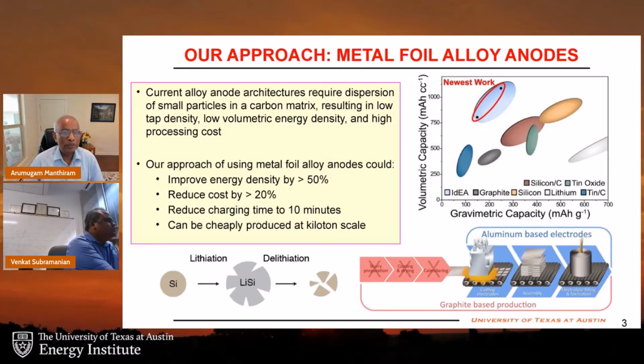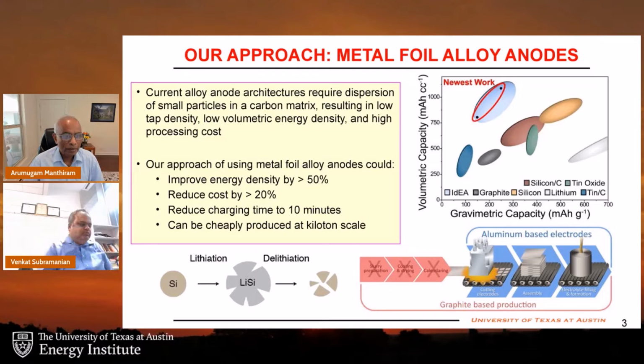So what is that new approach? Using metal foil alloy anodes. And this can potentially increase the energy density by more than 50%, reduce the cost by greater than 20%, and more importantly, they can also give potentially fast charge, a 10-minute charge. We all want to charge our batteries pretty fast, but right now we cannot. And they can also be cheaply produced at kiloton scale. So these will also eliminate, like I said, some of the steps involved in the graphite anode. The volumetric energy density with our new approach, as you see here, is much higher than the volumetric energy density we can get with other processes or other types of alloy anodes.